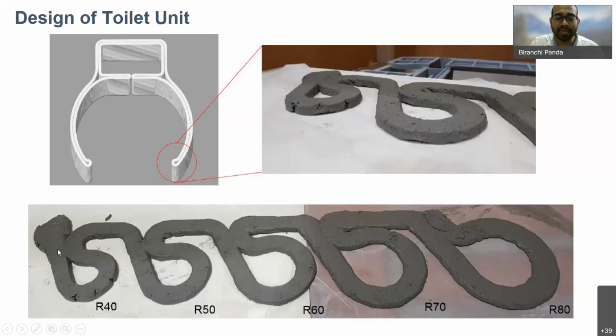Suppose you are printing with a very stiff material, you can always expect this kind of tearing of the surface. But even if you don't want to change the material and you want to avoid this tearing, the only solution is that you have to improve the radius of curvature. But from a design perspective, if you don't want to do that, what is the other solution? You have to make the material slightly more slumpy, so that even this sudden change in the radius of curvature or sharp turn is not going to affect it, because your material is now a bit slumpy. It's not stiff. With a stiff material turning very fast and a small radius of curvature, you are going to end up with such a scenario. But if you keep increasing the radius, of course, you are going to minimize this defect. At the same time, there are some other solutions, as I mentioned: your material can be slightly soft, and you can also go slowly during this turning. So there are many aspects that finally control the quality of your printed object.